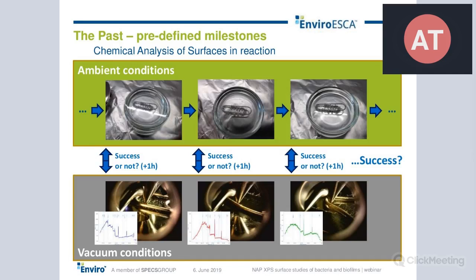The problem is that you only know if you had success when the sample is back in the machine, but finally, it is also very easily possible that in between some etching steps, you just missed the point where you start to see the interface between nickel and stainless steel. So even if you do this very properly, you still can miss the point and still might not have success. And then you have to repeat all of this procedure and all of this experiment again.